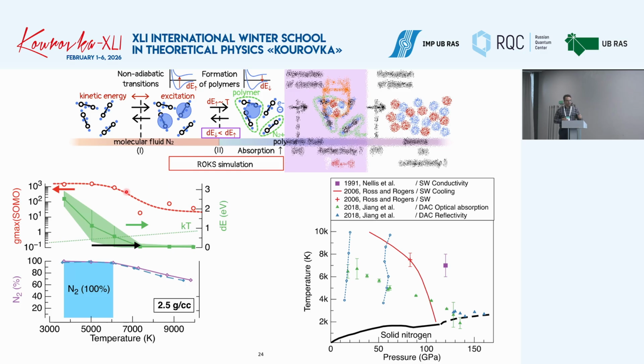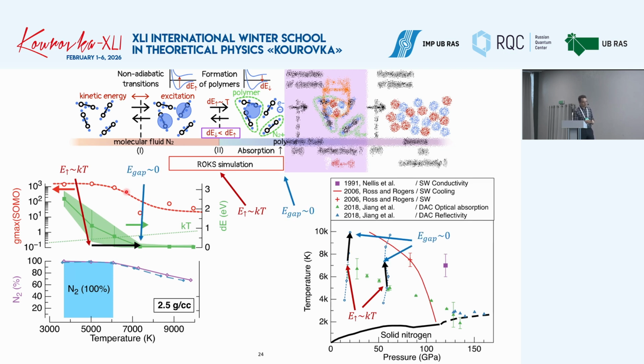So in case of fluid nitrogen, the same computational methods give another mechanism. So it is not exciton dissociation, but polymerization due to the closure of the band gap. And we were very happy that our points, shown here as these blue circles, correspond very nicely with the green symbols that are experimental points of the Goncharov group. No other work could before us explain these points of Goncharov.